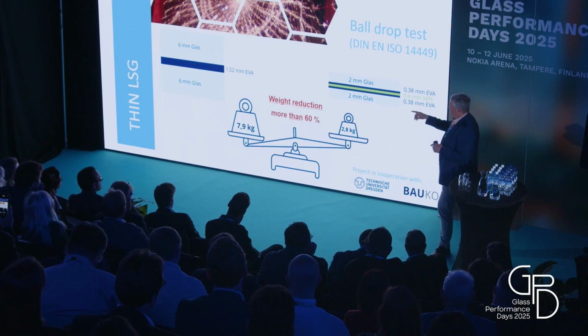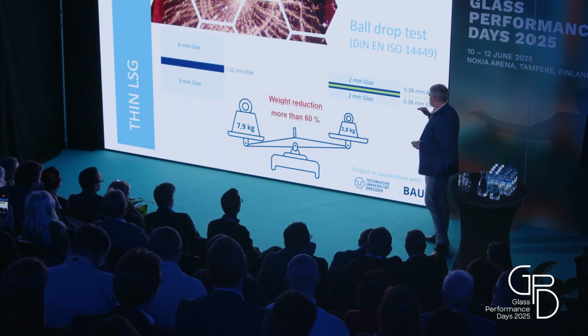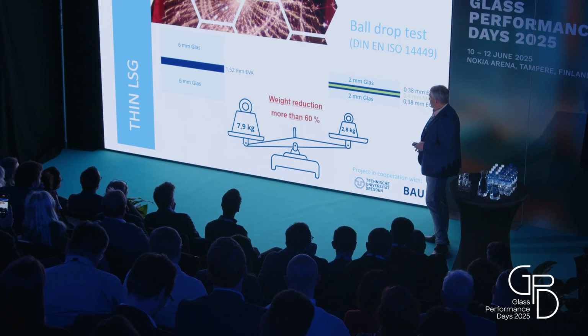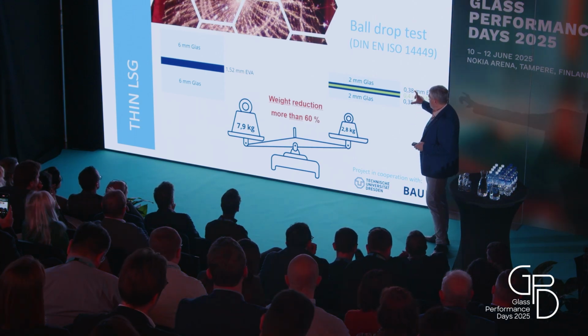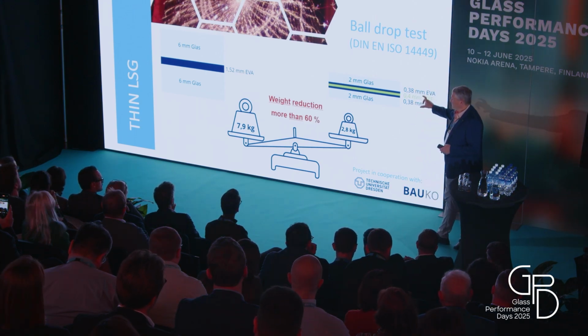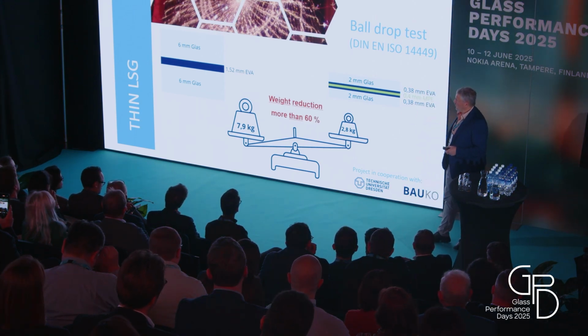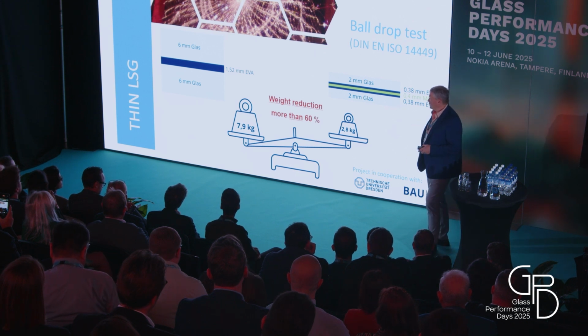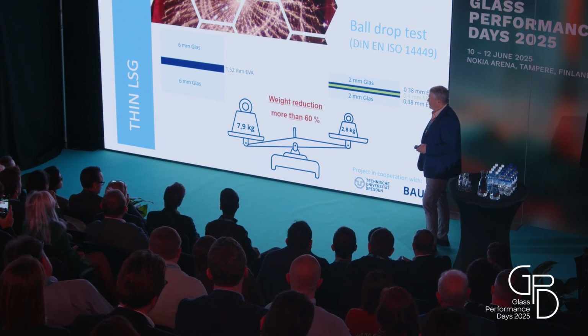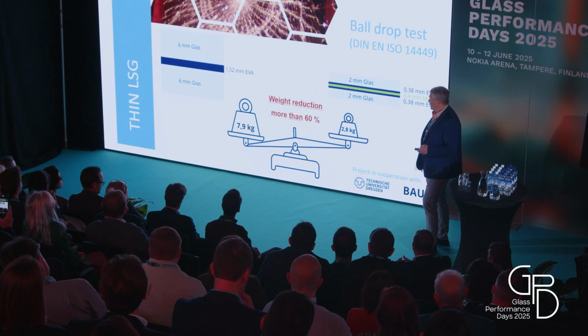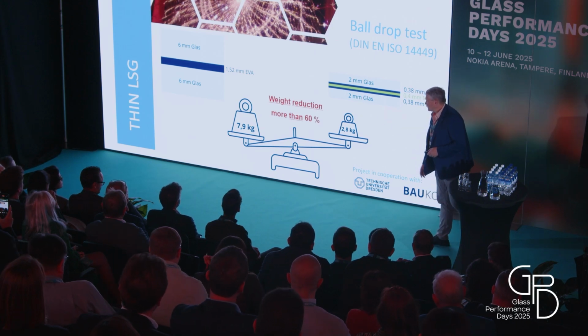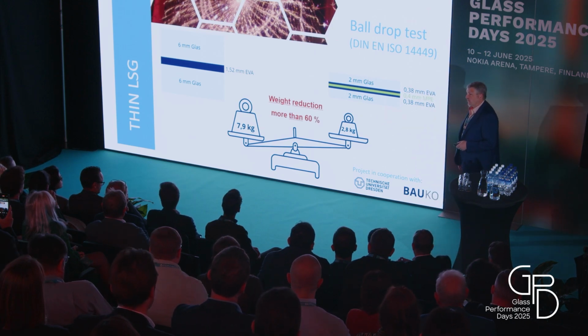And so we found out that by combination of the right interlayer, we are able to make such thin glass structures achieving the same ball drop height as, in this case, 6 millimeter thick safety glass. And this leads to a nominal weight reduction of more than 60%.